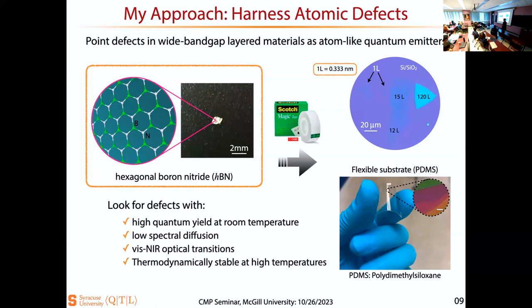So can I just ask for some clarification? Sure. It's not clear to me why you're able to locate the position of the defects in CVD grown compared to exfoliated samples. Okay. So let's say I make a CVD grown sample of 10 layers and I find a quantum emitter, then it will be within one of the 10 layers.